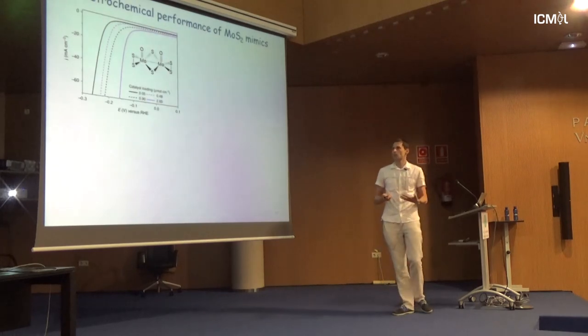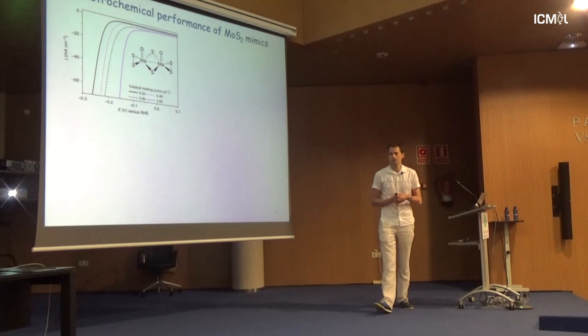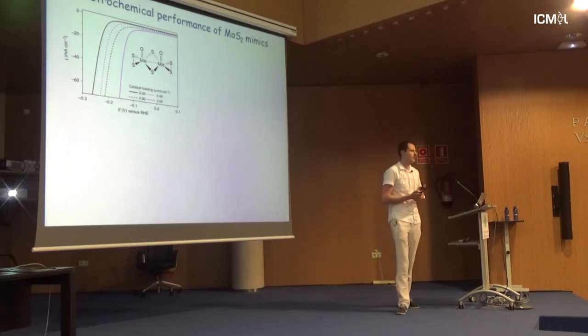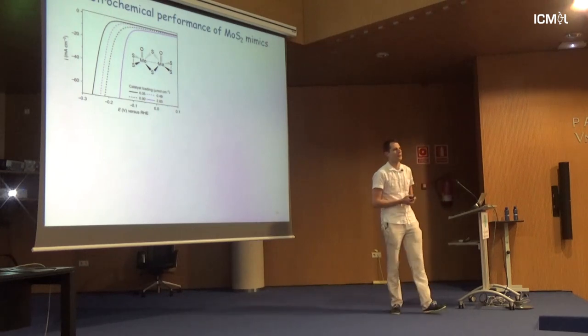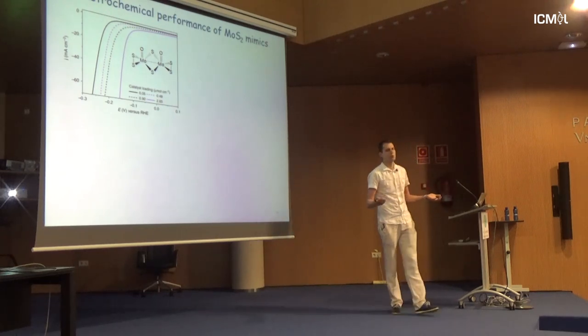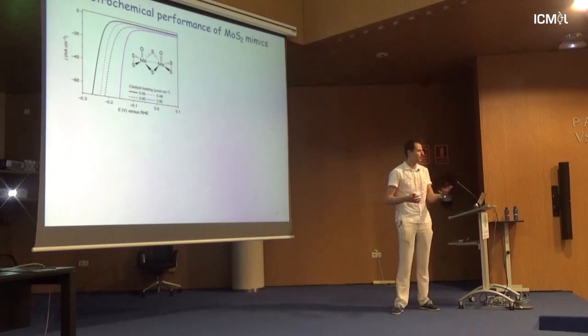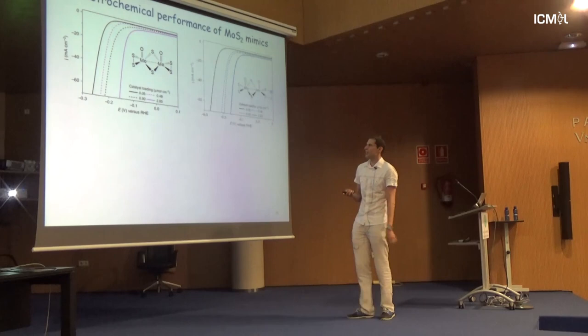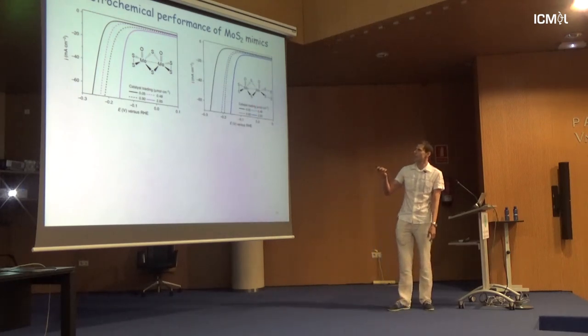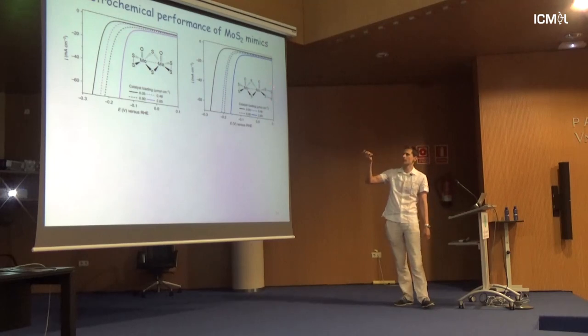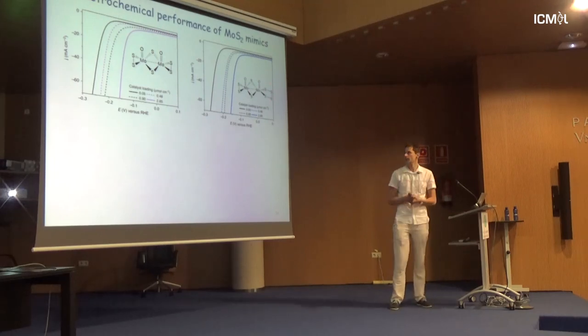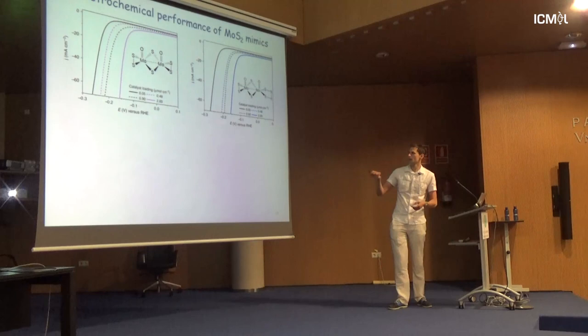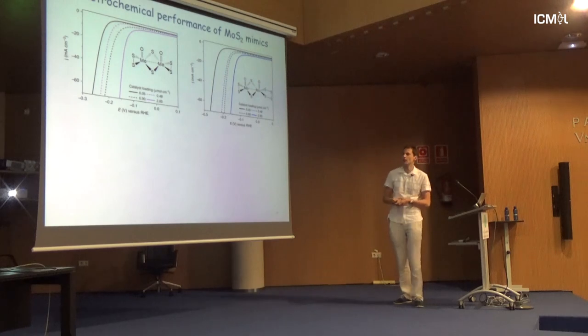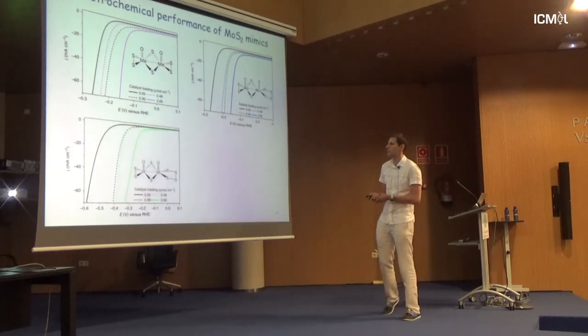And this is what you do. What you typically do, you do so-called cyclic voltammetry scans, and then you can also attach a GC, and then you look at the hydrogen evolution. So you play a little bit with catalyst loading. What was very interesting is that these two materials, despite one having this polysulfide tail here, perform practically the same. I think I should have plotted it differently on the same graph, but doesn't matter. If you see, they're basically spot on. They really have a similar performance. And that was very exciting.